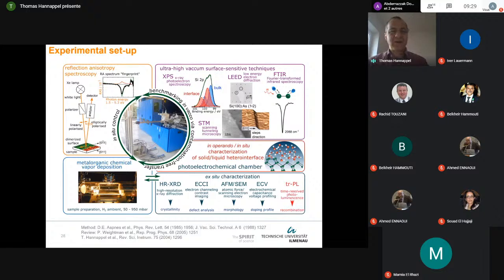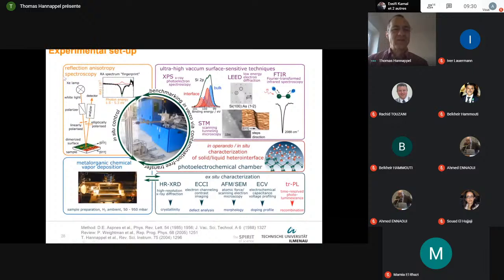For this, in our lab, we have created a way to look at our samples in very difficult chemical environments. This is the in situ optical spectroscopy, on the top left. Here, the so-called reflection anisotropy spectroscopy, which is more or less ellipsometry at normal incidence. However, it is very surface sensitive, very characteristic, very clear in its signals, so you can quantitatively evaluate your surface. It's a really strong tool.